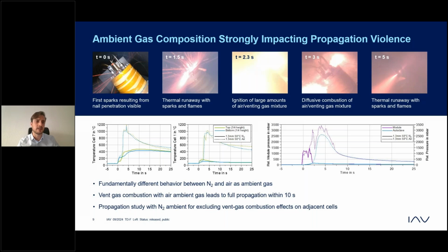And we can see that the temperature increases strongly when the nail is penetrated, and that's at 0 seconds. In the case with nitrogen, we see that this temperature increase is not as high as in the other case. It's because in the module we have the air which is inside the module starting to burn in the air case, which is not the case in the nitrogen case. In the nitrogen case, we just have the species composition of what is coming out of the cell, which is burning and getting into this thermal runaway of the central cell.